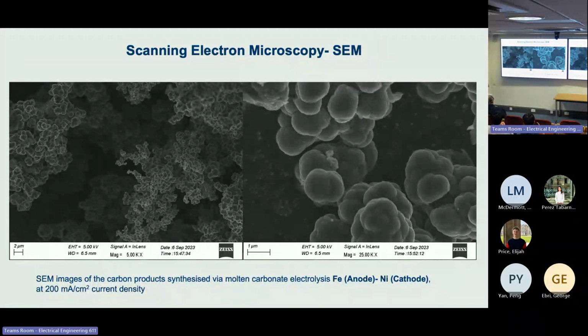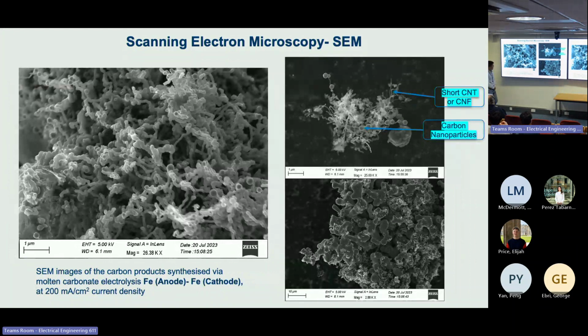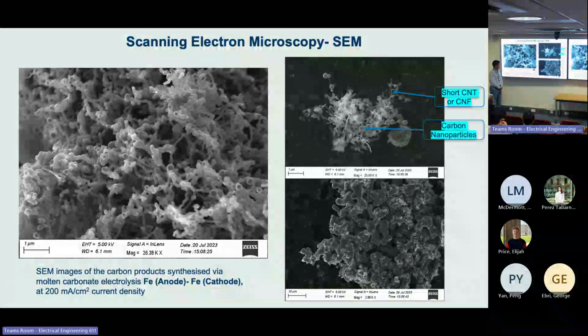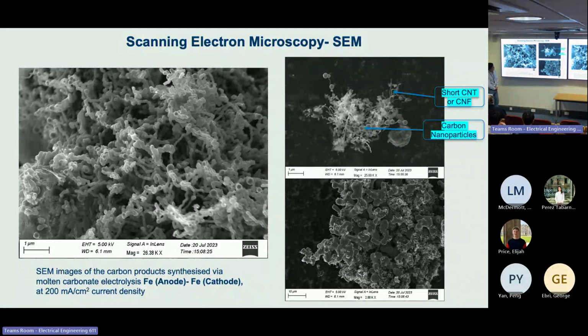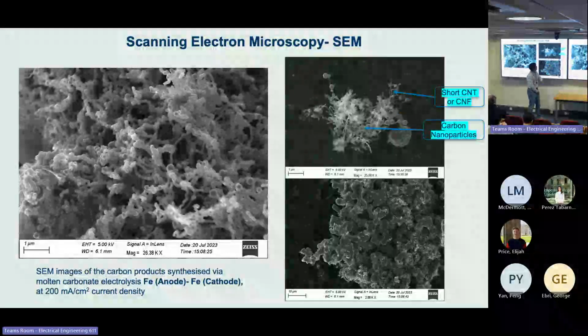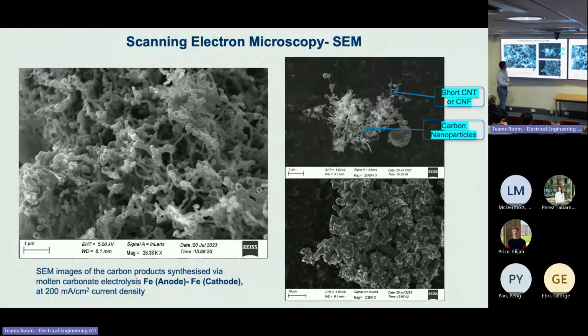Here are SEM images of the carbon products using the same current density, but with iron as the anode and nickel as the cathode. So we switched the two electrodes. No carbon nanotubes were observed, just amorphous carbon. Here we use iron electrodes as both the anode and the cathode. So we have some very short carbon nanotubes and also carbon nanoparticles and short nanofibers, but the majority is amorphous carbon.